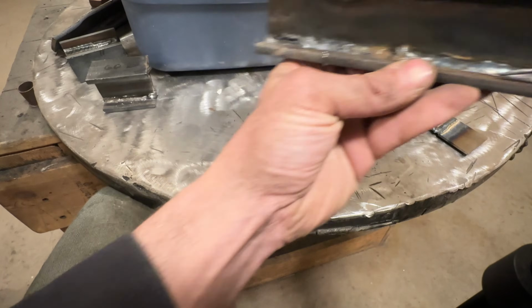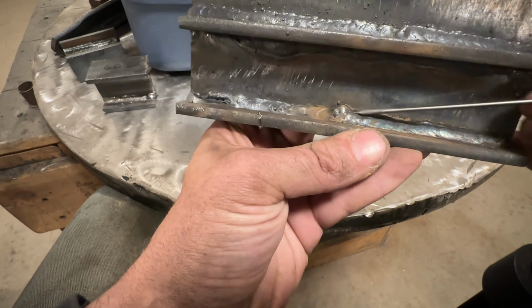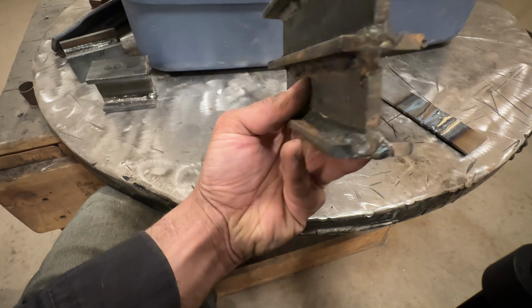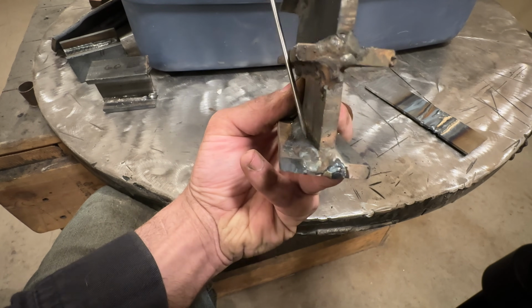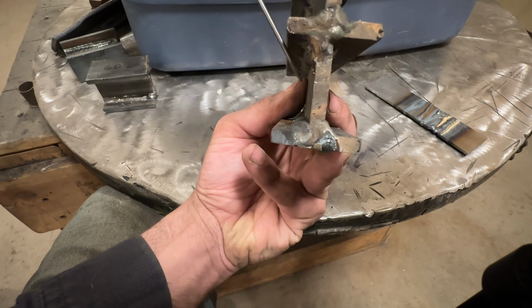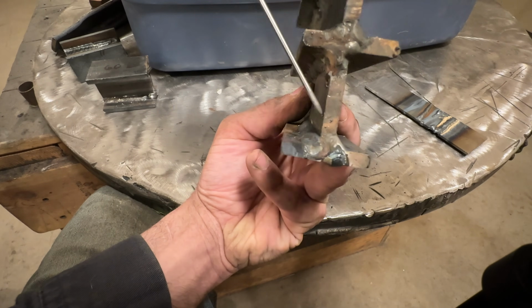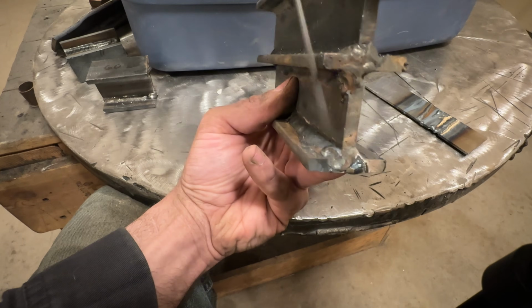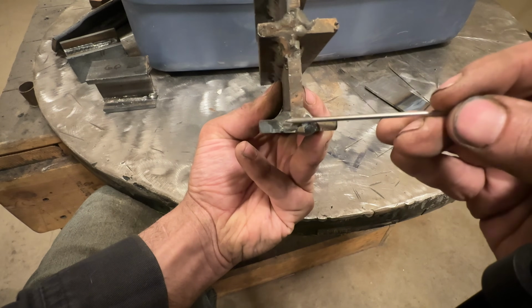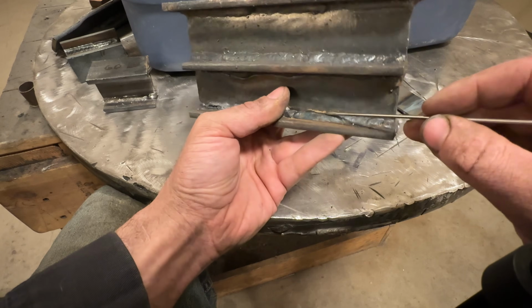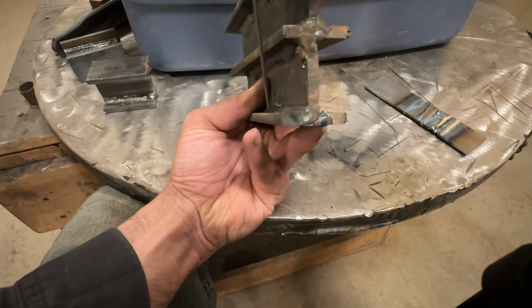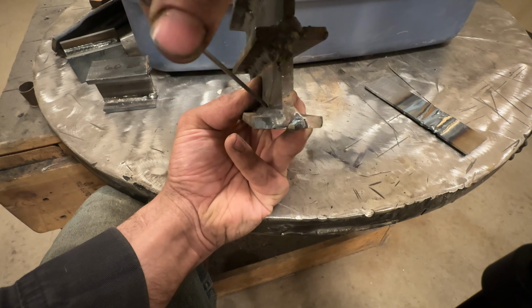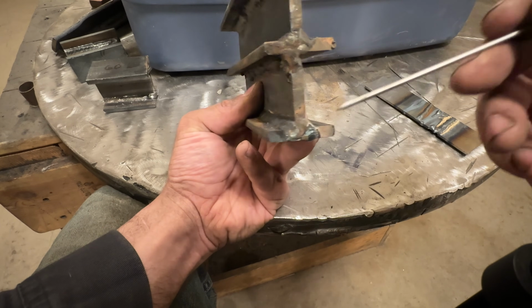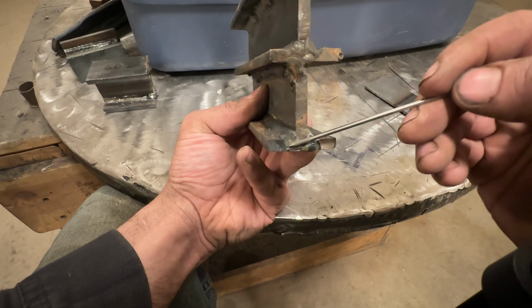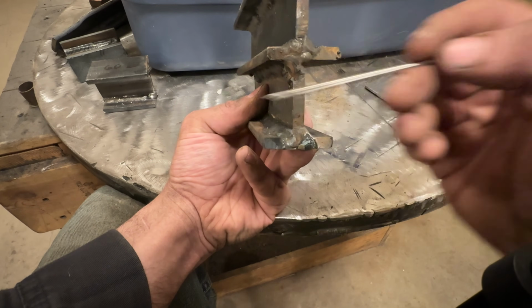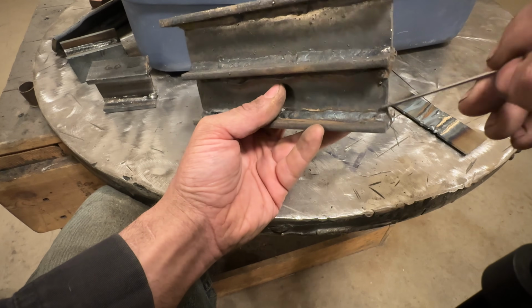Now this side, and I'll try and get the light better for you. This, if you look at it, the weld is like 90% on the bottom plate and almost nothing on this side plate. So that's a poor rod angle caused that. You know, the rod was coming in like this rather than like this. So is this a defect? Absolutely. If this plate were to get bent over towards this, like this, we have a very thin weld there, very weak.